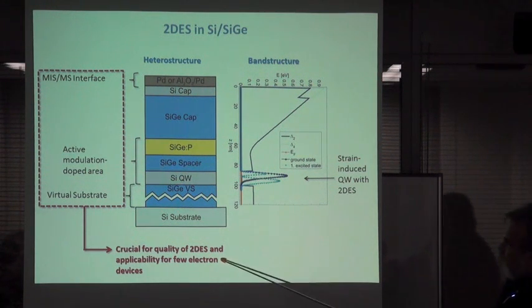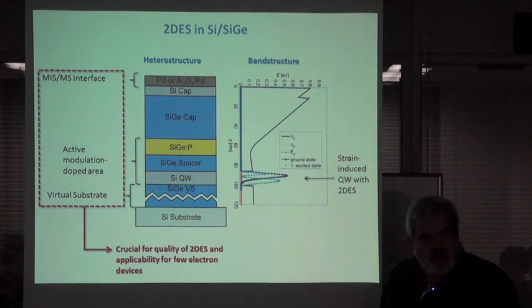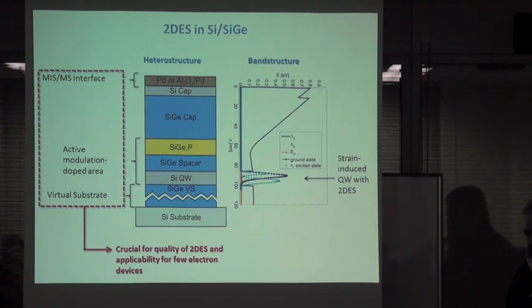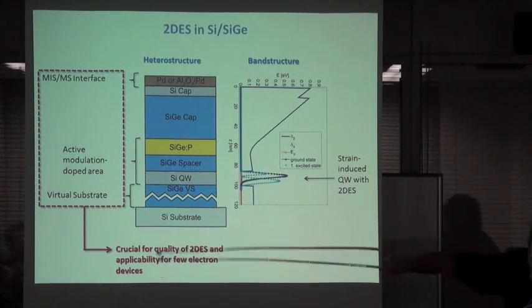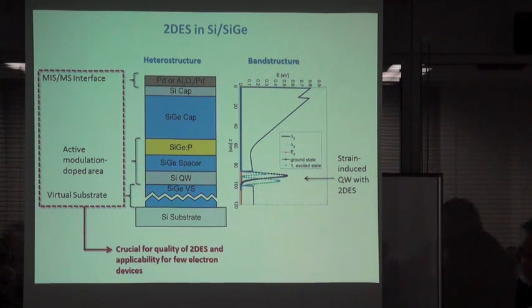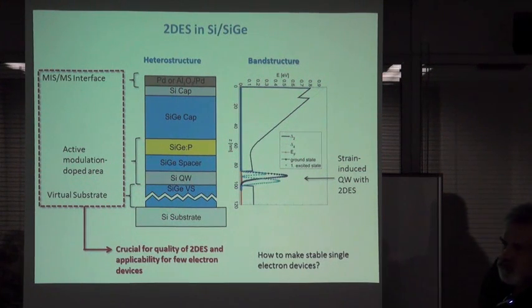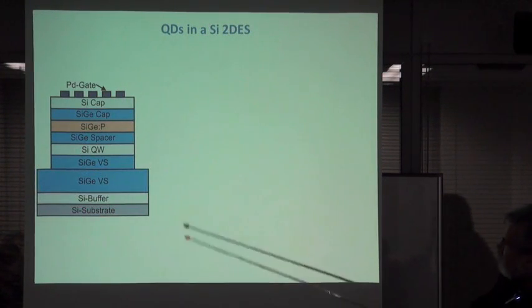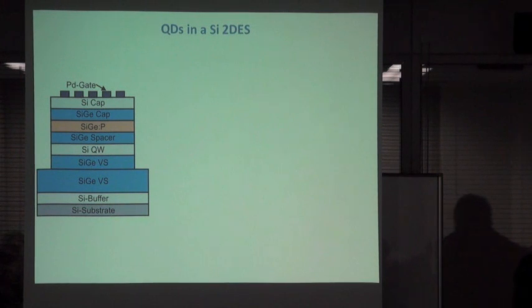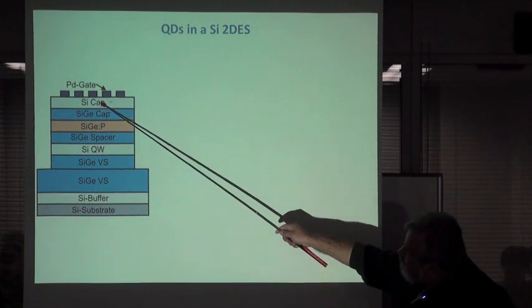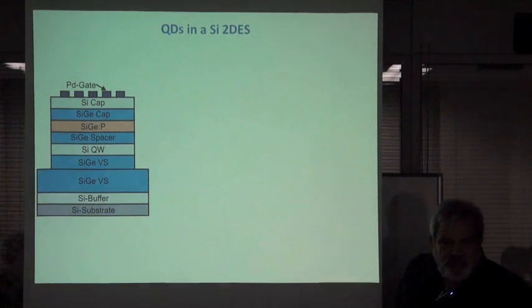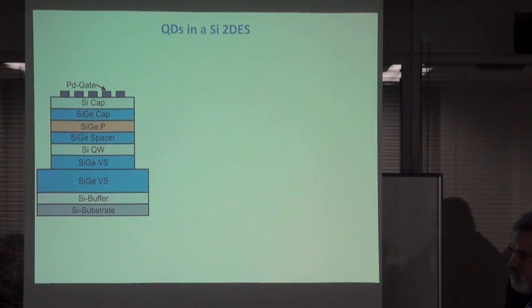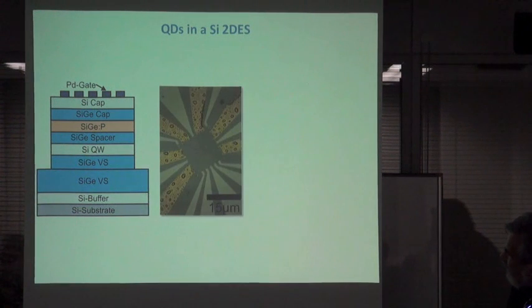So crucial for the quality is how you make this virtual substrate, because this is a graded buffer. You start with silicon and you want to have a virtual substrate with a new lattice constant, and normally you have a lot of dislocations and all kinds of problems, so this has to be optimized. And the next important thing for single electron effects is what kind of gate you are using. It turns out that palladium is a quite good Schottky gate for this. On top we have a silicon cap, so we have basically silicon technology here. So we use the Schottky barrier of palladium on silicon to tune the electron gas.